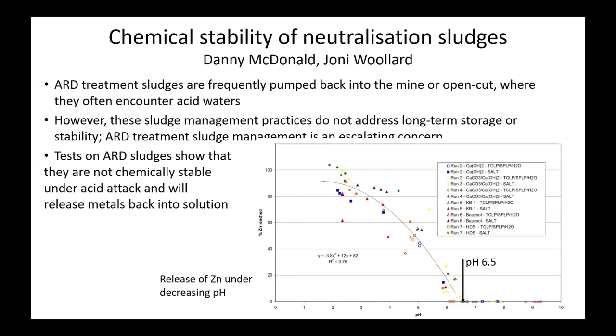So for this, Danny McDonald did his PhD thesis looking at sludges and what you can and can't do with them. And what he was concerned with is the fact that it's often very convenient to pump the sludges back into the mine. You've got a void right nearby, why not use it? And open cuts also. The trouble with that is the mine and the open cuts often have acid waters circulating through them. And so in terms of long-term storage and stability, that's a bit of an issue.